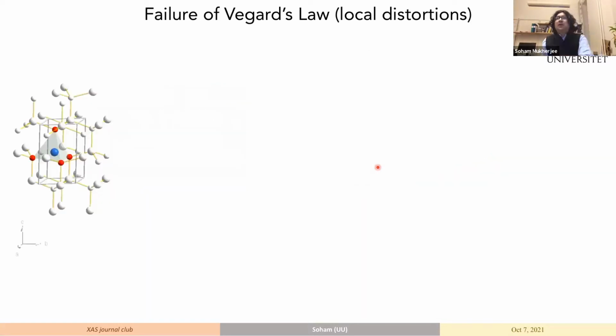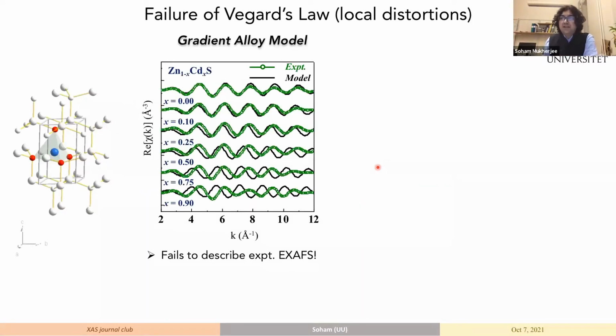But what happens next is when we try to model the XAFS. So this is just a simulation where we have put in different numbers of cadmiums into the system, and try to look at the experimental data, which has been done at the APS. We see that there is a gross mismatch, and the discrepancy increases as we put in more cadmium in the system. So what is going on?